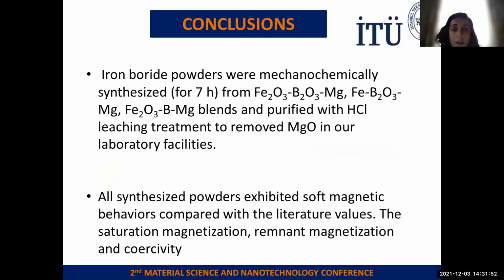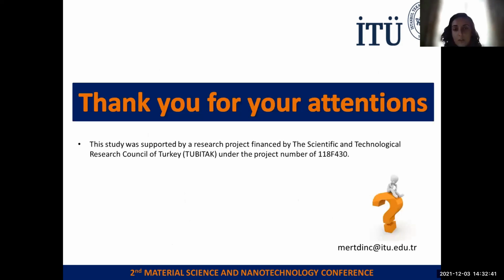And in conclusion, iron boride powders were mechanochemically synthesized for different durations from the different powder batches, and then they were purified using hydrochloric acid treatment to remove the magnesium oxide in our laboratory facilities. All synthesized powders exhibit soft magnetic behavior compared with the literature values, based on the magnetic hysteresis curves taken from the VSM results. Also, the saturation magnetization, low remnant magnetization, and low coercivity exhibit the soft magnetic properties of these synthesized nanoparticles.